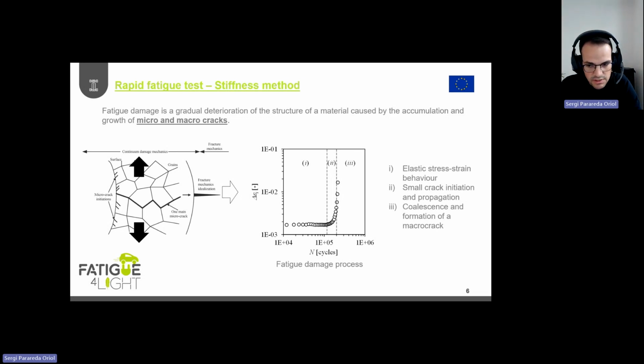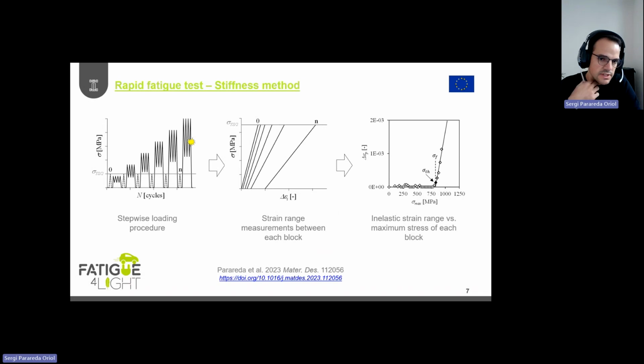Then we have this second stage where we have small crack initiation and propagation, and finally coalescence and formation of a macro crack. So the main idea of the stiffness method is to monitor this fatigue damage by measuring the strain at a given or constant stress value. As you can see here on the left-hand side, we are measuring the strain for a given stress, in this case, half of the yield strength.